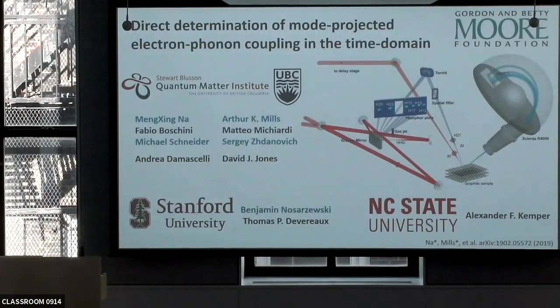You can do the same when you do resonant X-ray and things of this kind. And when you do this work with lasers, you're sort of stuck. You're transferring energy from the photon to the electron. The electron to come out of the solid has to pay about 4 to 5 eV of energy due to the work function. So when you go at 6 eV, you really have very little kinetic energy for the electron itself. So the idea here was to go at much higher photon energy and yet retain the resolutions that you need to do a proper work.